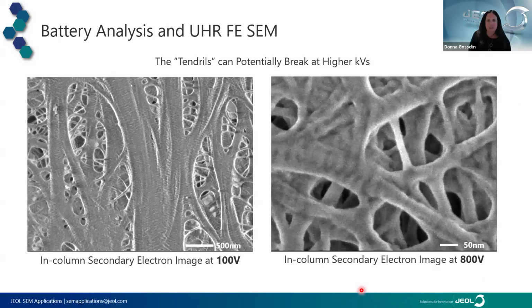Using that same detector, here are some examples of battery separator materials. Again, the power of these in-lens detectors is the ability to work at these ultra low voltages and really see fine surface morphology of the material. So in these images here, you can see that's a 50 nanometer scale bar, so we're at quite high magnification, and we're getting the ability to see crystalline morphology within the polymer.